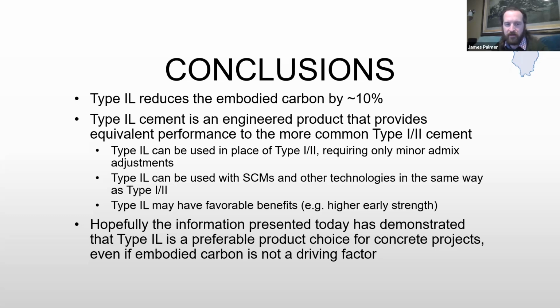The only caveat I would make there is that's for your standard mixes. When you get into more refined mixes with significantly lower water cement ratios, it may become more of a concern. And when I say lower water cement ratios, if you're in the 0.32 water cement ratio, you don't have as much free water to go around. So those would be the cases when it would be something you'd want to at least verify with a trial mix, though trial mixes are always recommended. We did do a trial batch with one of our partner companies last summer, and frankly, the finishers on that, and that was essentially a sidewalk mix.